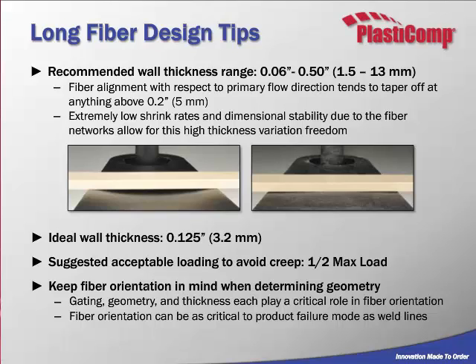Alright, another thing that's worth noting is fiber reinforced parts are much less susceptible to shrink. That being said, you can actually have thicker parts. That gives you a lot of design freedom. A typical range that we think is helpful is about 60 thousandths to 500 thousandths of an inch. Now that's going from our thinnest to the thickest pieces that we would recommend. I wouldn't go anything less than the 60 thousandths. Then you're going to start having trouble with higher fiber loadings flowing through your part. And at the same time, anything above 500 thousandths, your fiber orientation is much weaker because there's tumbling taking place. So that's why we recommend a thinner part.